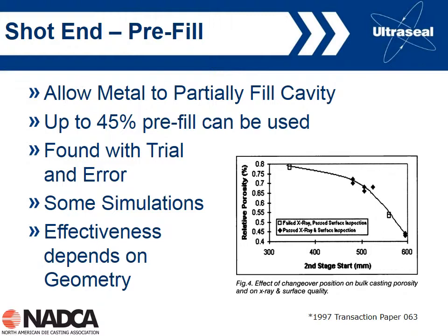Normally pre-fill is kept below 45% or so, and the graph at the bottom right here presents some data. Again, this is from a 1997 transactions paper. As we delay the onset of the fast velocity, so basically the second stage start is going from 300 to 400 to 500 to 600 millimeters, what it shows is that, at least for the conditions examined in this study, we were able to reduce the amount of porosity in the castings. And certainly a number of papers have shown this. We get similar results based on percent of castings passing or failing X-rays. So pre-fill can be beneficial. Basically, the longer delay of the fast shot, the lower the porosity.